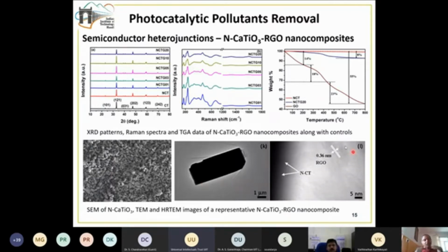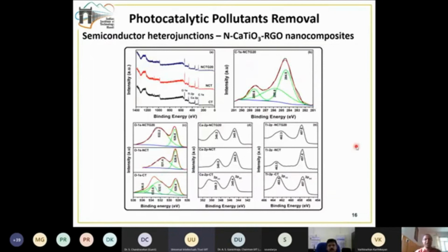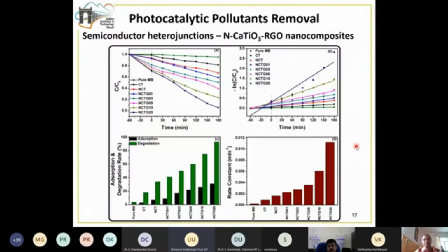Then we also did a very detailed XPS study in order to understand the oxidation state of each element in the sample, the electronic structure, and the interaction between the different elements present in the sample. Subsequent to the detailed characterization, we used this material for the adsorptive photocatalytic degradation of the pollutant.